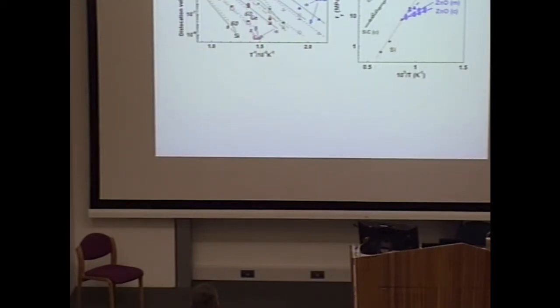And this is the dislocation velocity for various semiconductors, including wide gaps. As you can see, for silicon and compound semiconductors, the dislocation velocity can be described by this equation. And for wide gap semiconductors, we obtain only the yield stress against the temperature. From these relations, we can determine the activation energy also. So by using these relations,